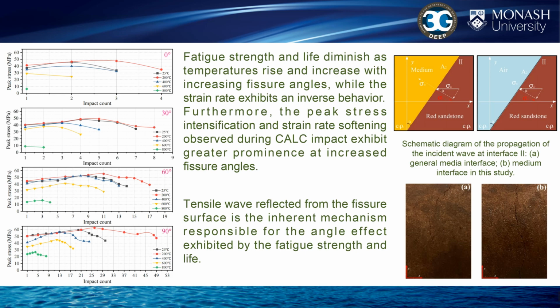Furthermore, the peak stress intensification and strain rate softening observed during CALC impact exhibit great prominence at increased fissure angles. The tensile wave reflected from the fissure surface is the inherent mechanism responsible for the angle effect exhibited by the fatigue strength and life.